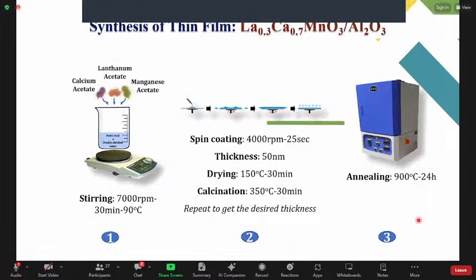This is the synthesis of this LCMO film. So onto the LaAlO3 substrate, we are depositing LCMO using the spin coater method by using the sol gel technique. For sol gel, we have used the acetates of calcium, lanthanum, and manganese in proportionate manner into the solution of acetic acid and double distilled water. Now this solution will be used for spin coating the LCMO layer onto the LaAlO3 substrate. Then we have done the annealing at 900 degrees Celsius for 24 hours.